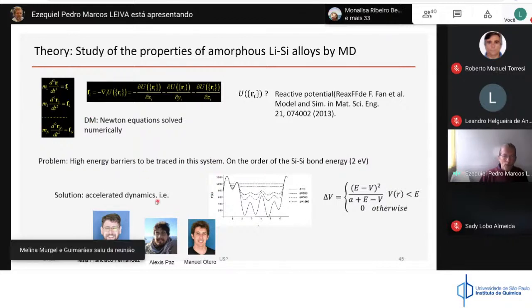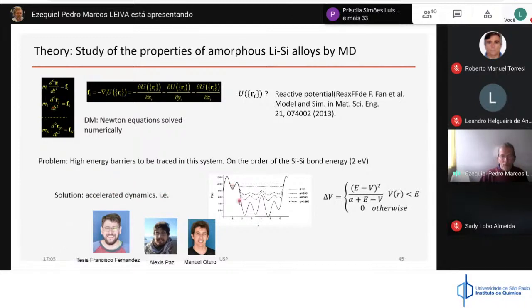What we did is use an accelerated dynamics, which is a version of molecular dynamics that modifies the energy, the free energy, or the energy landscape, allowing you to move the atoms much faster than with ordinary molecular dynamics. This is the PhD work of Francisco Fernandez, and this is collaboration work with Alexis Paz, who is a specialist in accelerated molecular dynamics, and Manuel Otero.